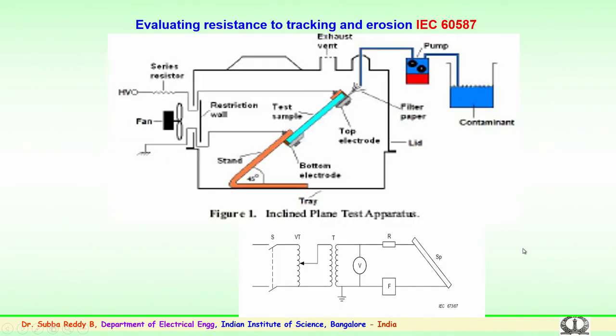Further, to evaluate the resistance to tracking and erosion, there is a standard, IEC 60587, which clearly gives the procedure to perform the experimentation on the silicone rubber or high temperature vulcanized rubber, where very clearly the 45 degree arrangement has to be made to fix the sample. This is the sample which is being fixed with the 45 degree arrangement.